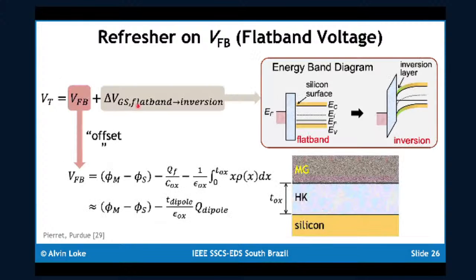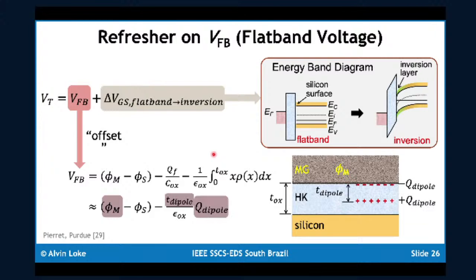Okay, now to achieve this offset, basically we look at the terms that impact the flat band voltage. It consists typically of three terms: a work function difference, a fixed oxide charge at the silicon surface interface, as well as trapped charge or fixed charge in the dielectric. So the way we are actually adjusting the VTs is through either work function adjustments or through the introduction of the so-called dipoles that we drive into the dielectric to basically adjust the threshold voltage or flat band voltage, which in turn adjusts the threshold voltage.